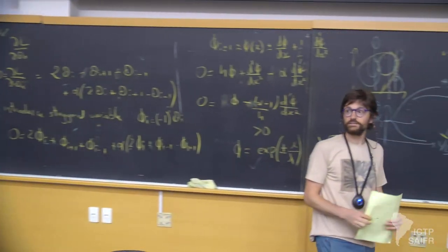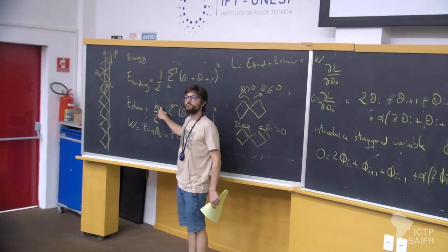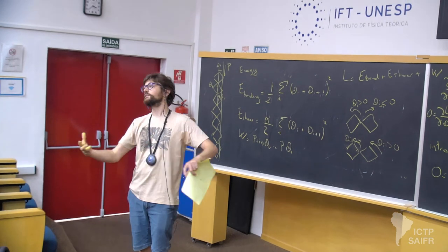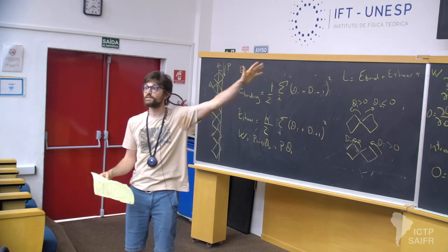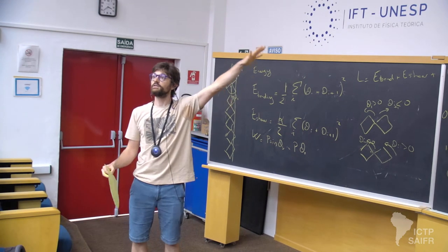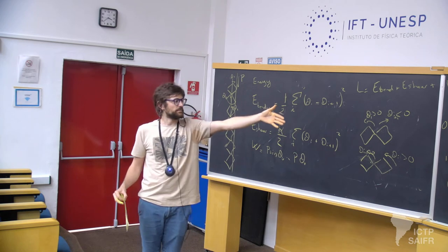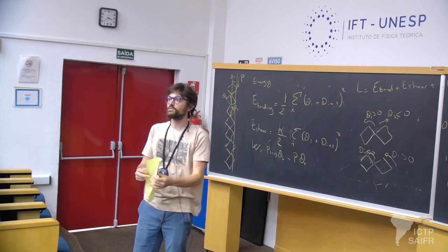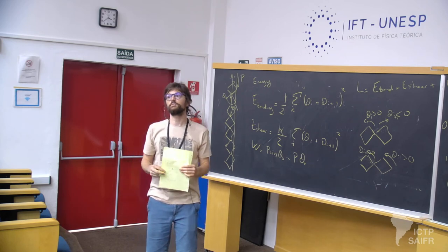And you see that the length scale, lambda, is actually given by alpha, and alpha tells you basically the ratio between your shear energy and your bending energy. So if it costs you a lot of energy to shear, you're going to have a longer decay, right? And we work very hard to make shear very expensive in comparison to bending. So in principle, we're happy with our printing when alpha is very large, because then it costs much less to bend than to shear. But ultimately, even with your best printing method, you always have a finite thickness, and so it's always a ligament that will have some finite energy. It's never going to be infinite to actually shear a little bit.